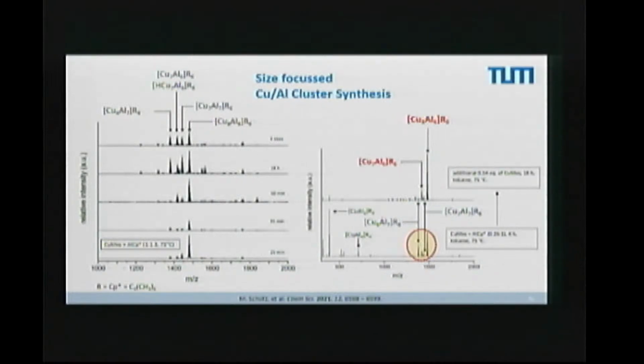However, if you look very closely, and I read these kinds of formulas to you, then let's say that we have these 4 peaks here. These are all molecular ions of clusters we could isolate from this particular solution. This is copper 8 aluminum 6. This is copper 7 aluminum 7. This is copper 6 aluminum 7. This is copper 7 aluminum 6. And it's a hydrogen atom, copper 7 aluminum 6. So all of these are super close in composition, plus or minus 1 metal atom.